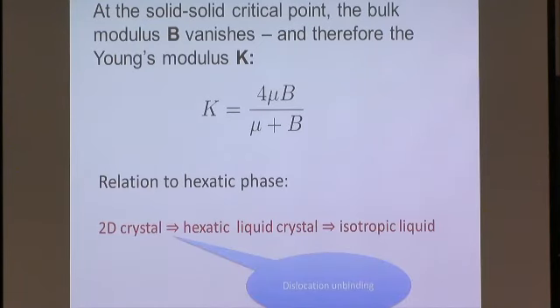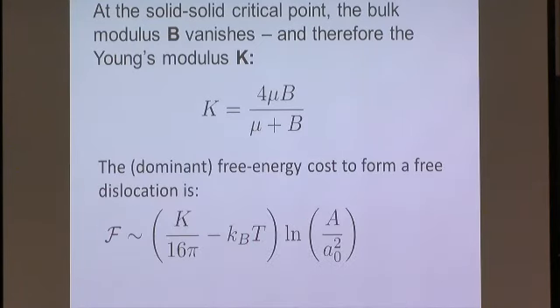Now, the dislocation unbinding, when does it happen? Very naive argument. There are two things that you have to consider. You have to consider the cost of making a free dislocation in a crystal, and in two dimensions that cost is infinite, at least if the surface area of the sample that you consider goes to infinity, then the cost goes to infinity, and it depends on the Young's modulus and some numbers. Actually, I left out the lattice constant, but I say suitably dimensionalized numbers. That's what you have to pay.